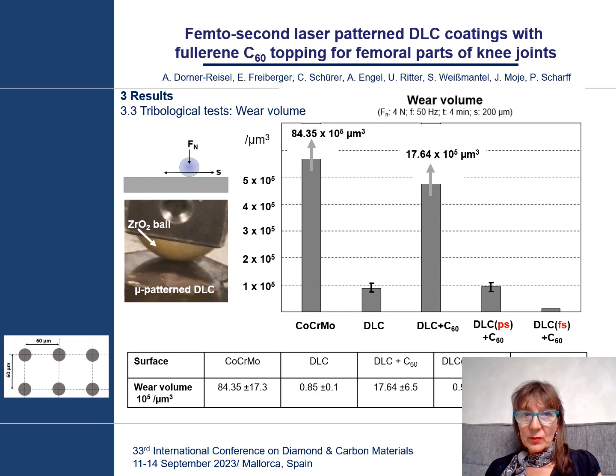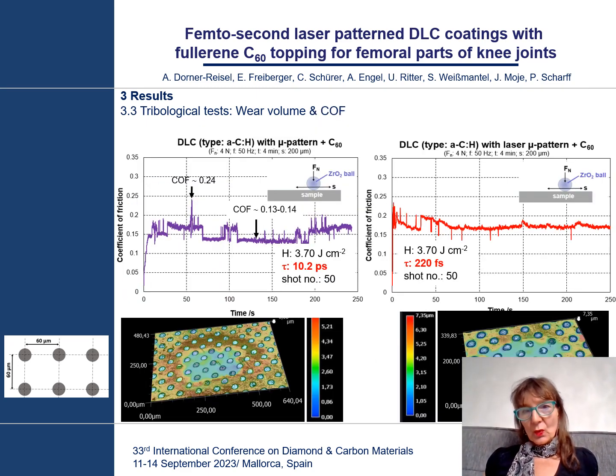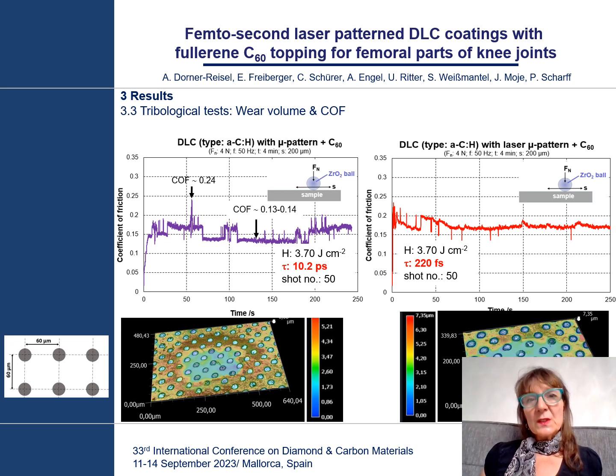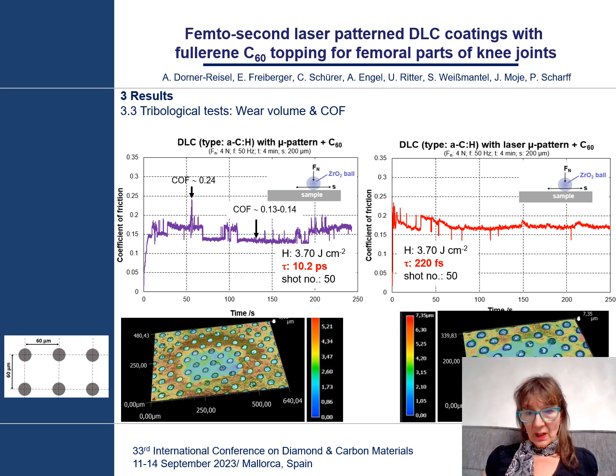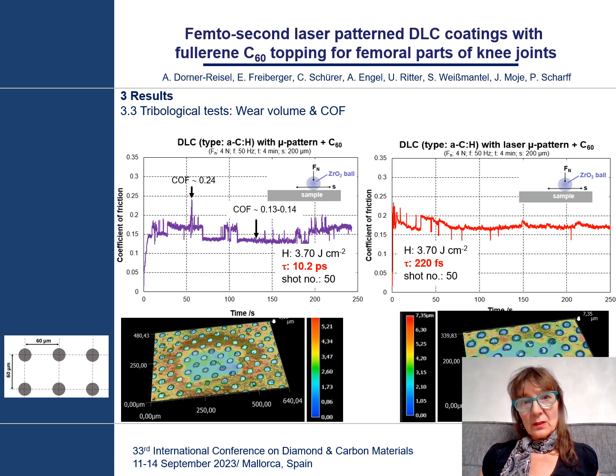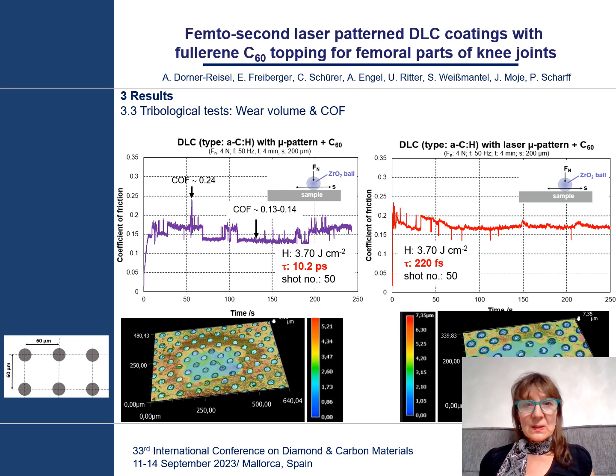DLC with picosecond laser patterning and C60 topping, however, showed an increased wear volume in comparison to diamond-like carbon without patterning and without topping. On this slide, you can recognize the coefficient of friction curves of femto and picosecond laser treated diamond-like carbon coatings with C60 topping again. Also, you can see the digital images of the wear traces. And it is known that transfer film formation on DLC is associated with hydrogen release from the coating. However, if this hydrogen household is mixed up or hydrogen is set free before tribological loading, there is a reduction of the hydrogen and the volume expansion which is related with the hydrogen release.